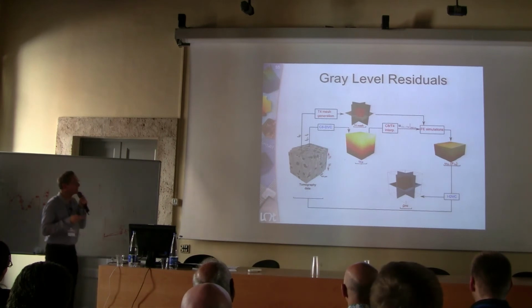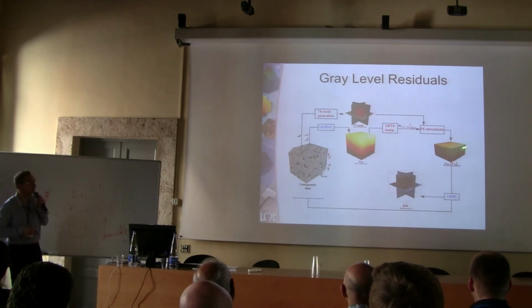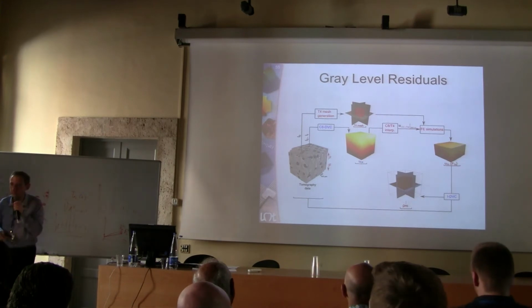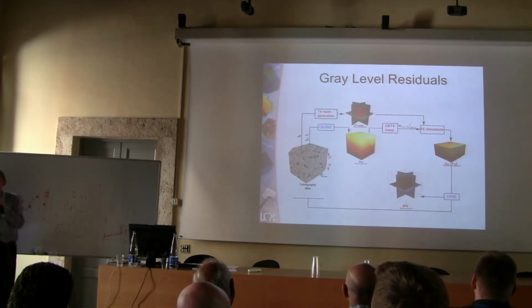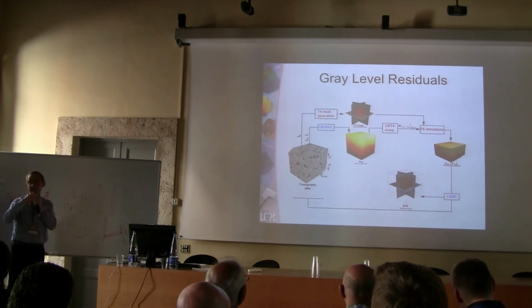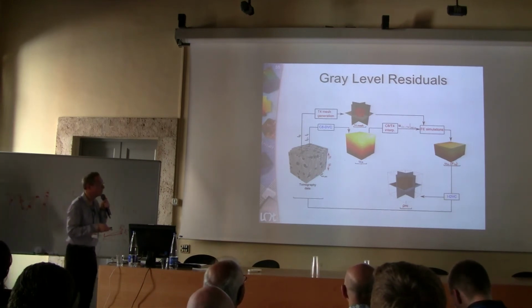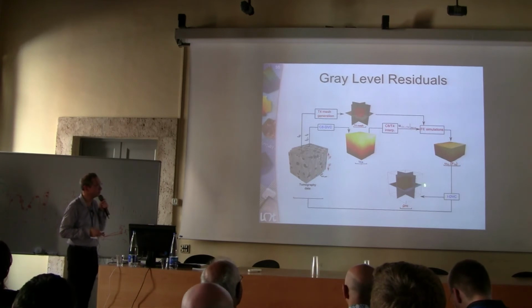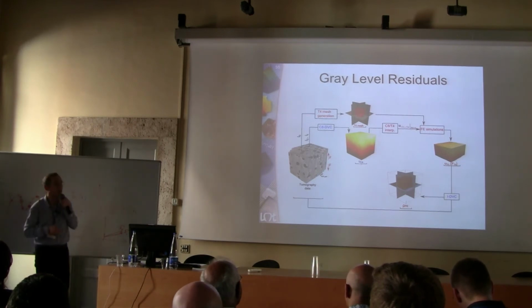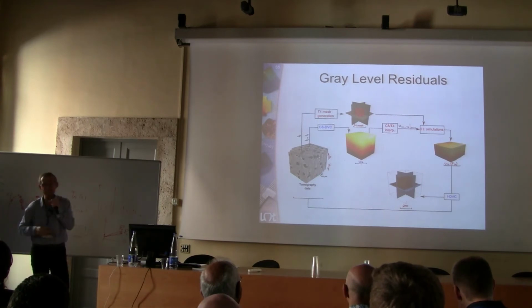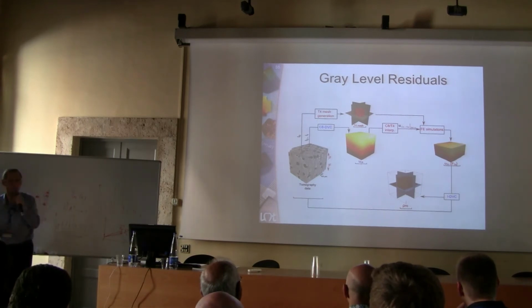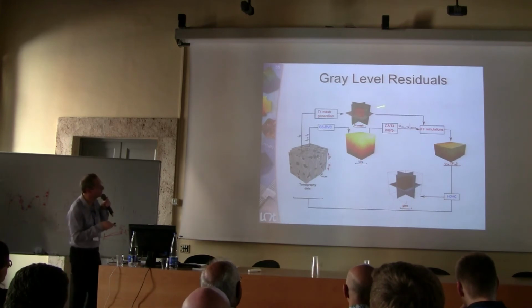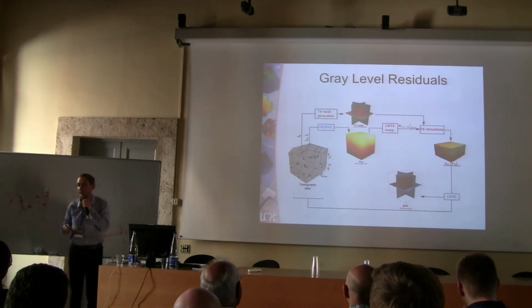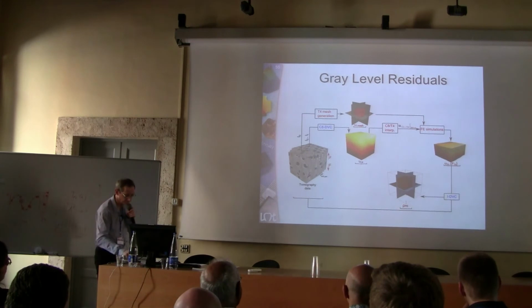Anyway, the fact that these simulations were driven by measured boundary conditions allows you then to also compute the gray level residuals independently from the previous case, which means that this allows you to compare the performance of this procedure in comparison with the direct procedure where you only use DVC. And remember that the mesh is a lot finer in the numerical simulations.